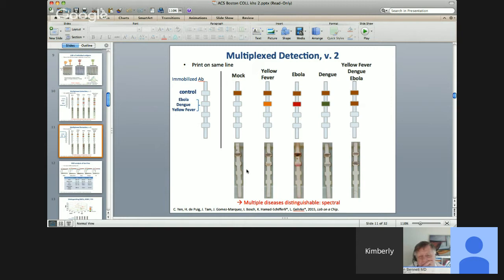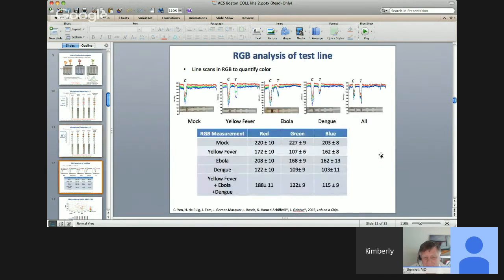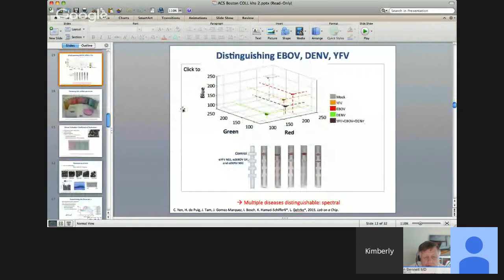Now, if you look at this, my eyes are old, and to me, these colors all look kind of similar, and so you might say, how can you distinguish between them? This doesn't really look very orange, and this maybe looks kind of brownish, but I'm not really sure. So what we did is we actually quantified this using image analysis. We detected the RGB channels of each of these. I won't go into too much detail, but we do line scans of these and quantify the RGB values of each of those test lines. And we can see here that we can distinguish it. So this is the RGB values for each of those tests.